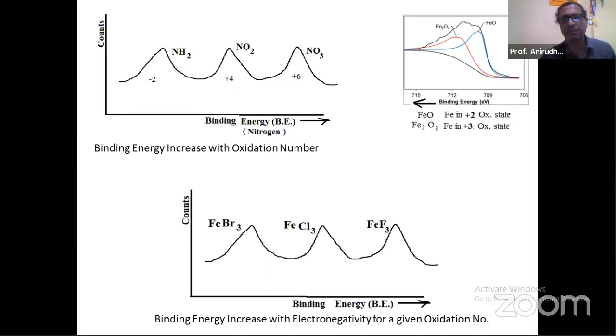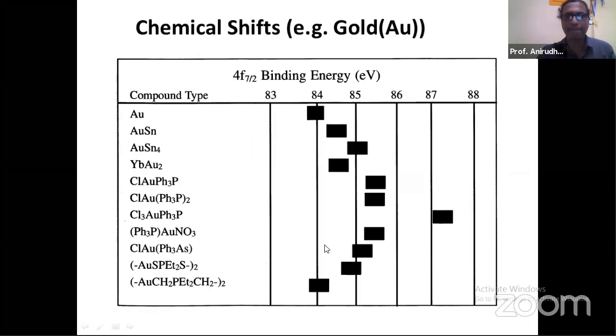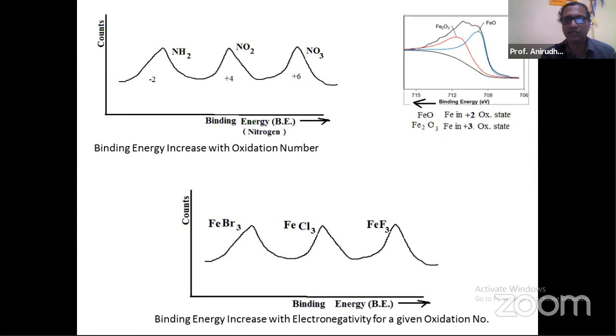Now, by the same argument, for a given oxidation number, the binding energies would change according to the electronegativity of the element which is trying to bond with this. I've shown a figure below, similar to the one shown above, where we are looking at iron bonding with bromine, chlorine and fluorine: FeBr3, FeCl3, FeF3. The oxidation state for iron is the same in all these cases, but the electronegativity of fluorine is higher than that of chlorine, and that of chlorine is higher than that of bromine, which means these valence electrons are pulled with greater and greater affinity by the neighboring atoms.